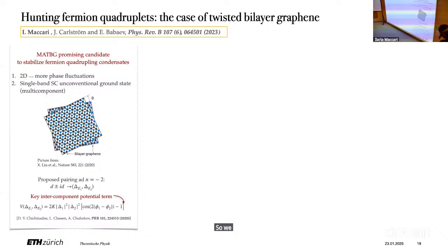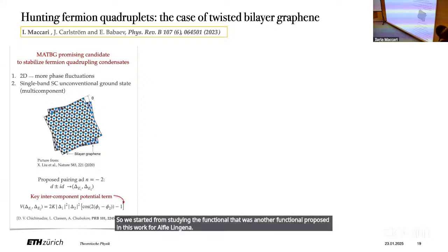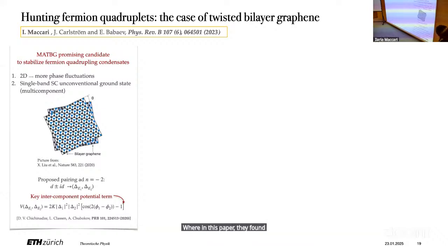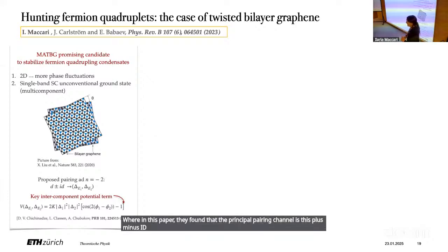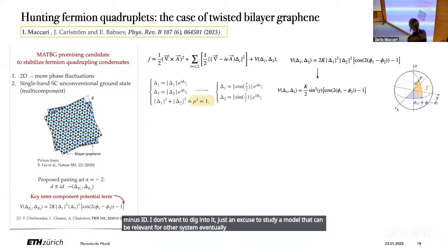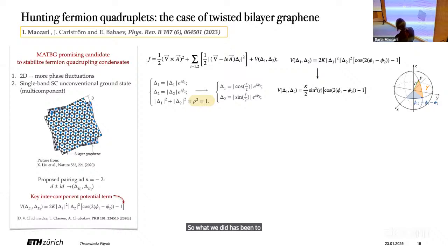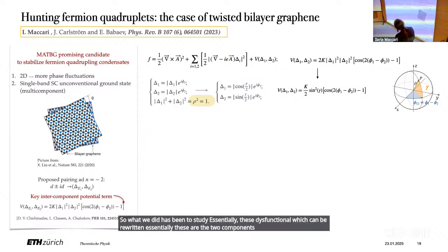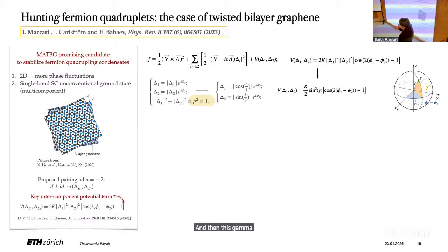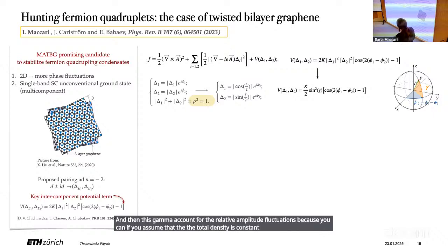So we started from studying the Landau functional proposed in this work by Fernandes and collaborators, where in this paper they found that the principal pairing channel is this plus minus id. I don't want to dig into it, it's just an excuse to study a model that can be relevant for other systems eventually. I know it's still very debated. What we did was to study this functional, which can be rewritten as a function of two angles. One is the phase difference between the two condensates, and then this gamma accounts for the relative amplitude fluctuations, because if you assume that the total density is constant, you can rewrite these two amplitudes in terms of sine and cosine of this gamma.